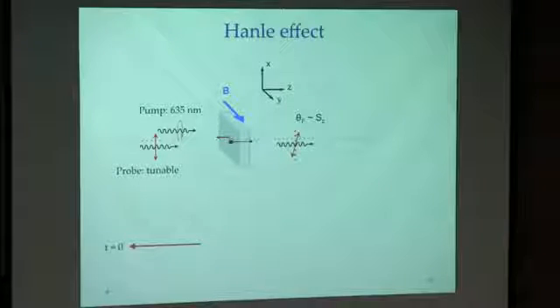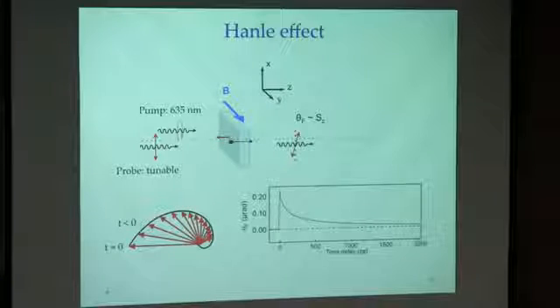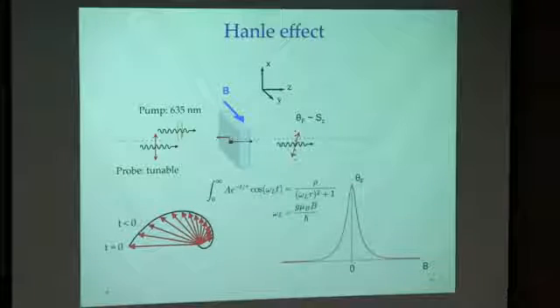So now the measurement, since it's steady state, is a time integration of all the spin signal in the past. And we know that the time resolved data shows this is how it looks in zero field, and that's how it looks in some external magnetic field. So as we do the integration, we get some positive signal. But for oscillations, they're going to cancel out. We get a really decreased signal in magnetic field. As a result, the signal decreases with magnetic field. And how fast it decreases, from the width of this curve, from the width of the magnetic field response, we can also infer the spin lifetimes here.